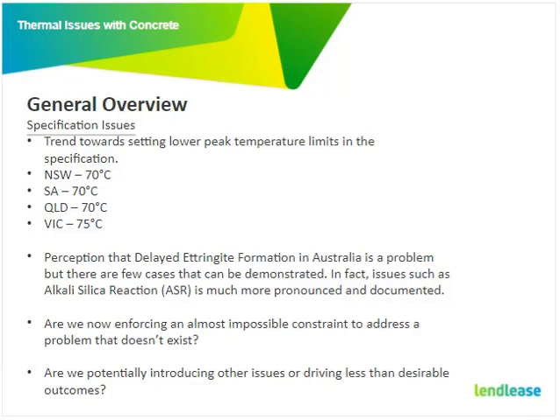I don't know where this has come from. There's a perception that delayed ettringite formation in Australia is a problem, but you do a lot of research and you basically can't find many issues. So why has it been enforced? There are many other issues when you look at inspecting older bridges, such as alkali silica reaction, which are much more pronounced and documented.